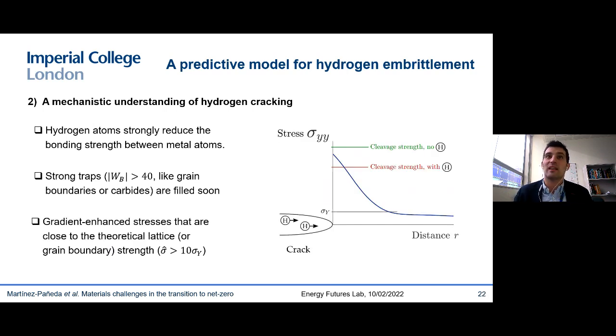If you couple that understanding with the microscale plasticity models that I showed you before, what you see is that in the absence of hydrogen, the cleavage strength, so the strength at which you switch to brittle failure, is too high. Your stresses are not high enough, so they don't interact, and then you need other mechanisms. You need those voids to nucleate and grow and coalesce.